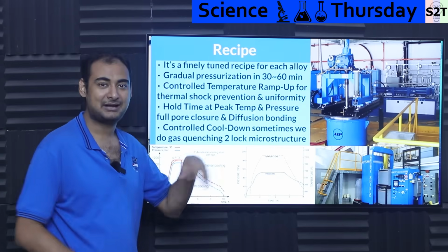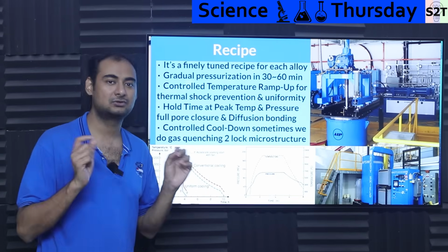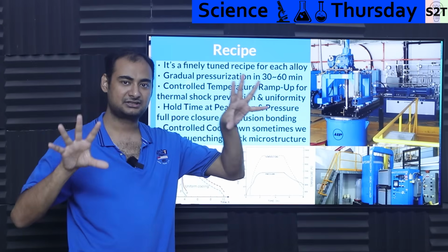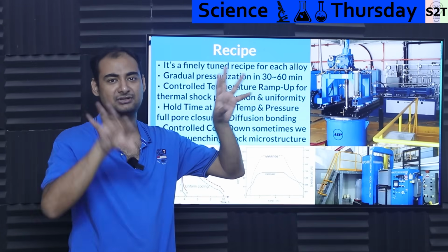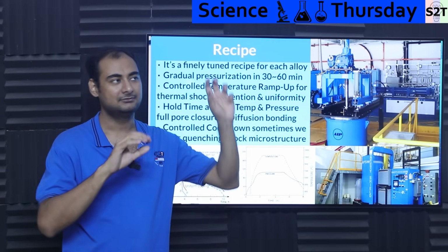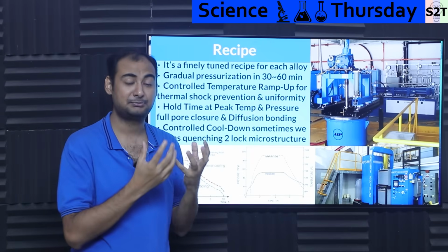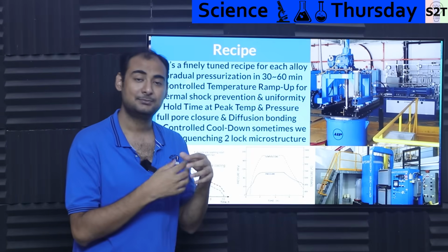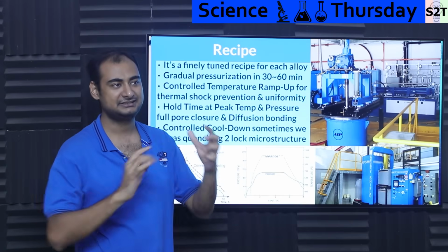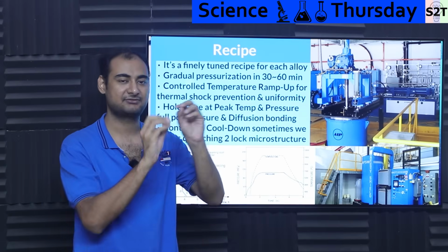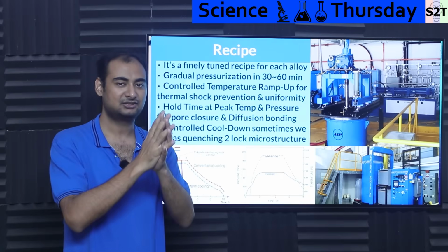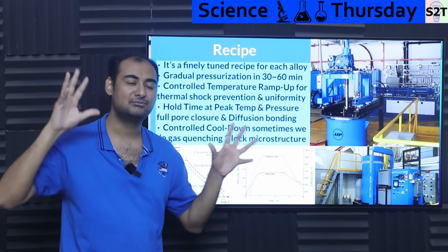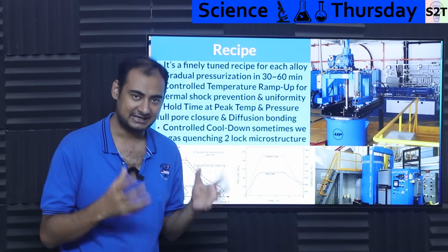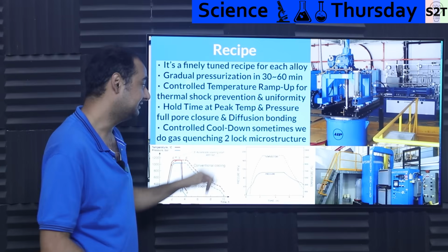Now this is where magic happens. This is where basically pore closure happens. Basically you have giant crystal grains that are awesome, strong, but they are surrounded by tiny small ones. Bad. What happens when you have this sort of plasticity? Basically you have pressure and temperature that is plastic enough, and then these things start to get married together. Instead of hundreds of small units, they start to combine into larger units, and now you have much less grain boundary. So that removes all the porosity, and diffusion bonding happens.